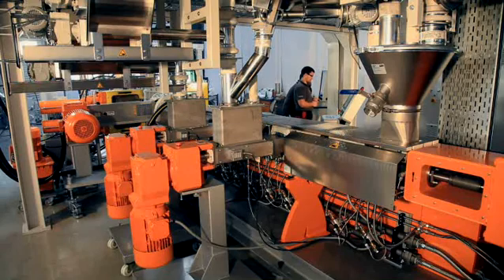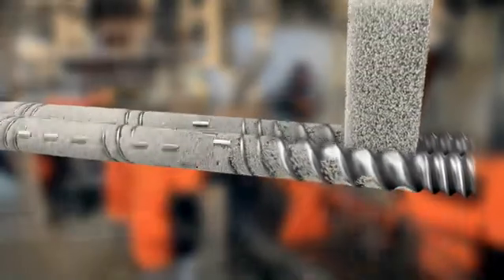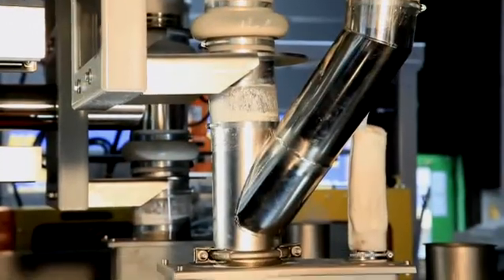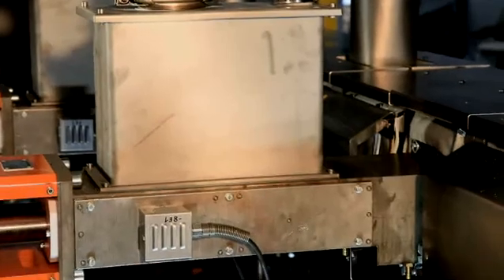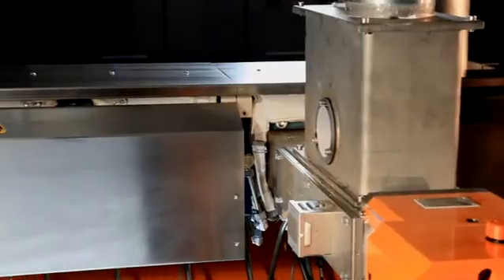Let's have a look at how the process was realized here. We start with the melting zone. First of all, the polymer and a small amount of dispersion aid are melted. Via the first side feeder, the first share of filling material is added. In the upcoming kneading zone,